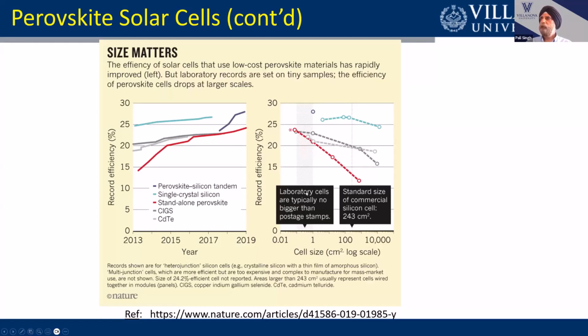However, the efficiency drops off significantly as you increase the size of the cell. And so lab cells originally were no bigger than a postage stamp. And in terms of these high efficiencies, but now there are standard cells that have been manufactured that are larger in size.